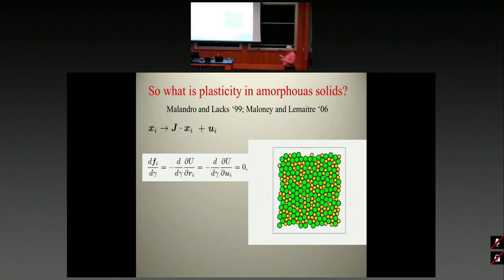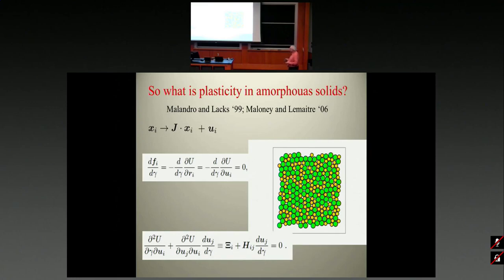What does it mean? So here's the interpretation. So firstly, of course, the energy itself is directly affected by the gamma. I make a change in the positions of the particle, an affine change. The energy is going to change. So one contribution here is going to be the second partial derivative of u with respect to gamma and ui. I have one partial to ui. There is a direct dependence of u on this gamma, so I have a second derivative here. And then the ui itself, how much non-affine response is there, is also going to depend on this gamma.